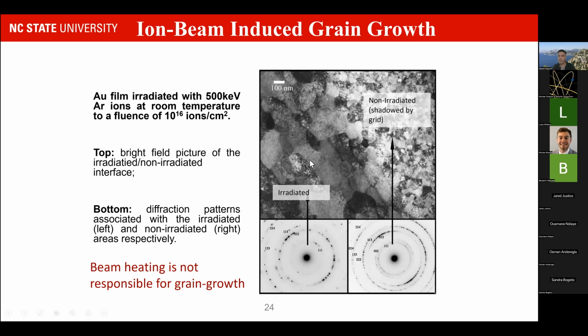And this is a typical picture that we could observe with a clear delineation between the irradiated area where you had evidence of grain growth and the non-irradiated area nearby where there was no grain growth. So this also was a further proof that ion beam heating is not responsible for grain growth. This type of grain growth is due to the irradiation process itself. If it was due to beam heating, you would have thermal heat conduction because those films are metals, and you would not have a very sharp delimitation between non-irradiated and irradiated region. You would have grain growth all over the place.